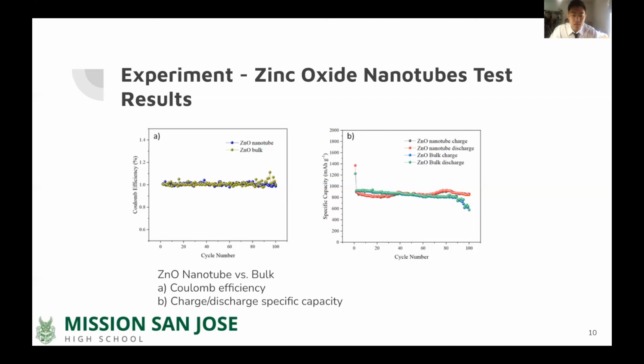From the graph, we can see that the initial Coulomb efficiency for zinc oxide nanotubes is less than the initial Coulomb efficiency of bulk zinc oxide, which are around 0.655 and 0.752 respectively. This can be explained through the structure of zinc oxide nanotubes with more area. The specific area for the nanotubes is a lot greater than the specific area of bulk zinc oxide, which means there are more points of contact for the lithium ion to bond to on the nanotubes. As a result, more lithium ions become trapped in the anode as well, causing a greater decrease in the initial specific capacity to form an SEI film.